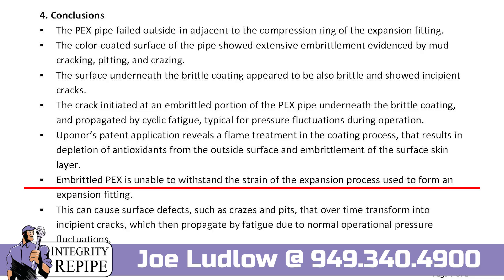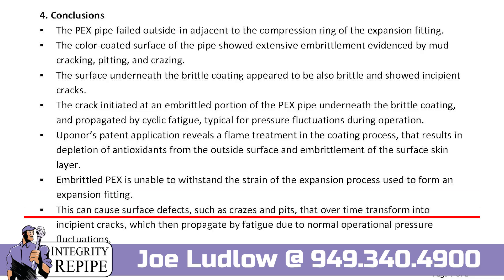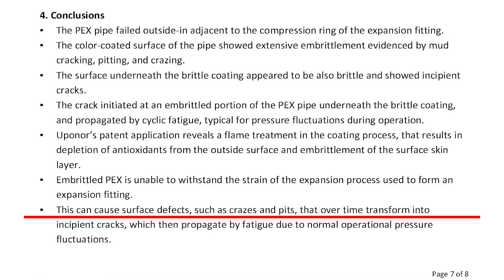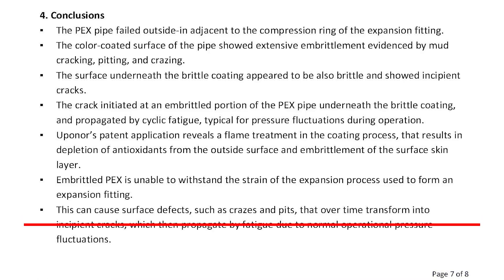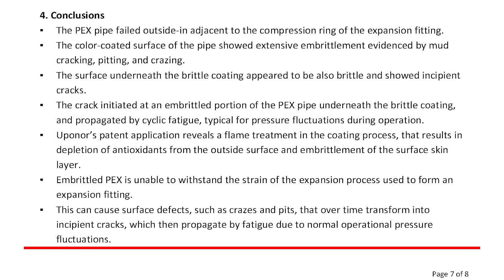Embrittled PEX is unable to withstand the strain of the expansion process used to form an expansion fitting. This can cause surface defects such as crazes and pits that over time transform into incipient cracks, which then propagate by fatigue due to normal operational pressure fluctuations.